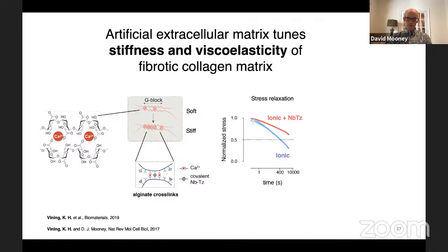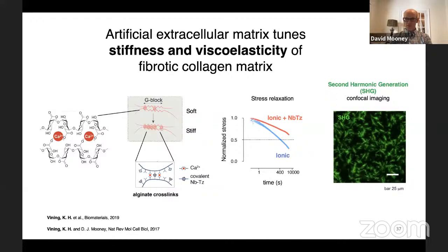And by this, he could create materials that would have varying rates of viscoelasticity, as indicated by varying rates of stress relaxation, without changing any of the other features of the system, such as the collagen fibril formation, the mesh size or porosity of the gels, or other features.